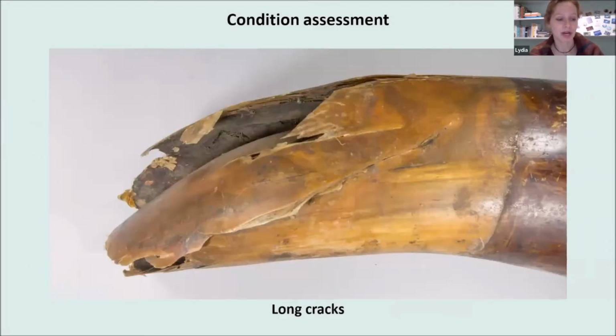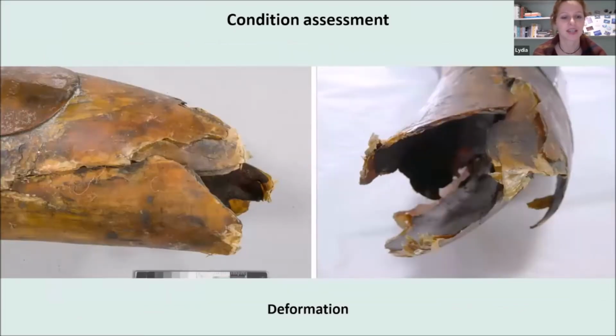The bandages were also hiding large longitudinal cracks, which are extending from the break edges. I counted 14 cracks in total, and the longest crack measured 22 centimeters in length. The cracks promoted further damage, such as the deformation of broken sections. I assume that the horn had been stored with a significant weight on the broken areas for some time, and this caused the material to collapse inwards and to overlap along the break edges.